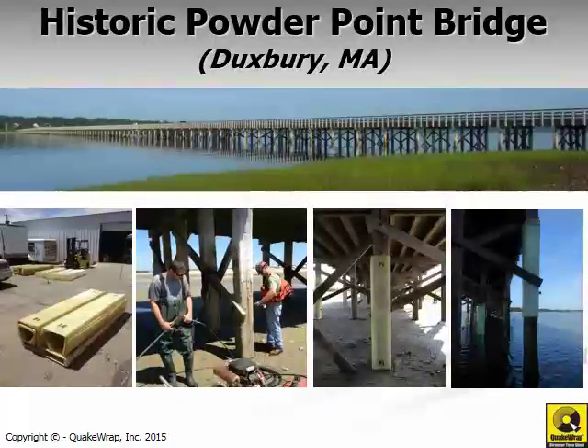Our patented system, as I explained before, can either use the laminates, as you have seen in some of the previous slides, or it also covers when we use these prefabricated shells, as you see here. In this case, these shells are 2 half shells like a U shape, they are brought together and put around the column. As you see here in the lower bottom portion, you can put 2 4-foot sections to create an 8-foot tall shell. The shells can also be above water and pushed into water at a later stage.